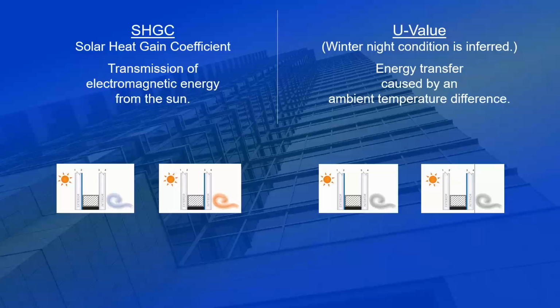Now, as far as low E coating placement is concerned, if we look over on the right-hand side, you'll notice that there's no difference in U value whether that low E coating is on the number 2 surface or the number 3 surface. However, if that coating is on the number 2 surface, from a solar heat gain perspective, because that coating is outboard of the airspace and protecting that airspace from more solar heat gain transfer, you have a lower solar heat gain value for the IGU. If that low E is on the number 3 surface, which is not uncommon for projects in Alberta, for example, that low E coating will provide a higher solar heat gain coefficient for that IGU.